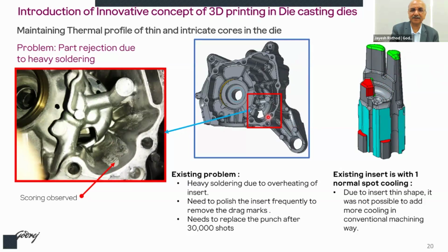Because of this, the temperature increases to such an extent that aluminum sticks to the tool steel and soldering occurs. Many times the casting gets stuck in the die and is very difficult to remove, or aluminum material will remain in the die even after the casting is ejected. Then it affects the surface finish of the casting, and many times casting production stops here. Because of this, a lot of rejection occurs. And the important thing is, since there is no cooling channel here, the life of this insert is hardly 30,000 shots, whereas the normal die life goes up to 1 lakh shots or 1.25 lakh shots.